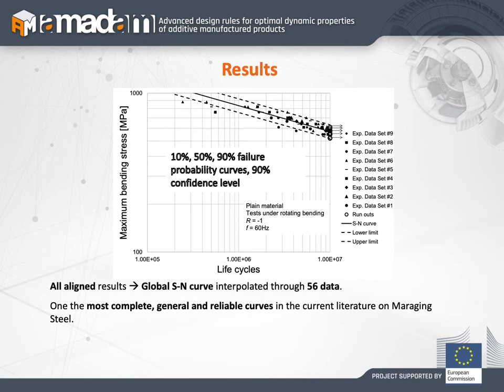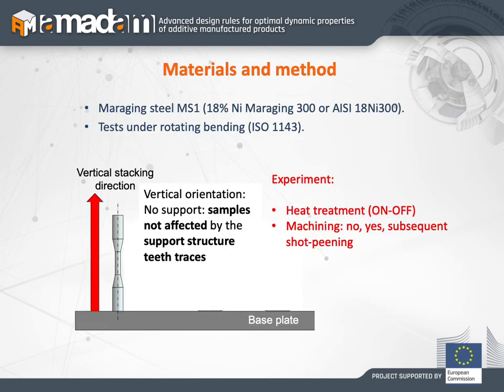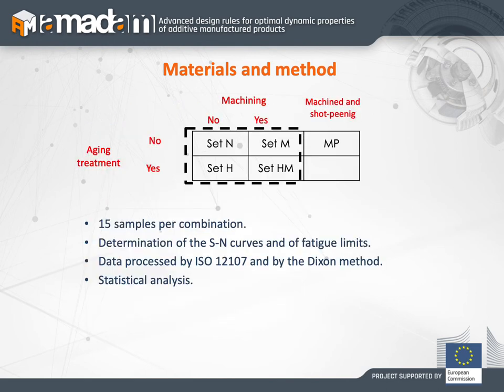So, starting from this fact, we considered a new test campaign with only the vertical direction, since the other two directions are not significant in the results of the fatigue test, and we consider to have or not have the allowance. As I told you before, we consider testing the specimens as they are, without any machining before testing. And also the combination of the aging treatment. So, having a look at the table of the tests, we can see the presence of machining, no or yes, and the aging treatment, no or yes.